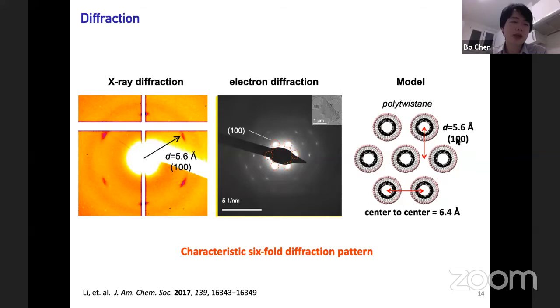And we have tried a reasonable set of hydrocarbons that might have this six-fold symmetry, for example, graphene, and some other 3D CH network. None of these can give us a diffraction pattern that matches experiment. So we took this as very strong evidence for the formation of nanothread from benzene. The d-spacing of 5.6 angstrom translates to a center-to-center distance of 6.4 angstrom, which includes not only the width of the thread, but also the van der Waals spacings between them.